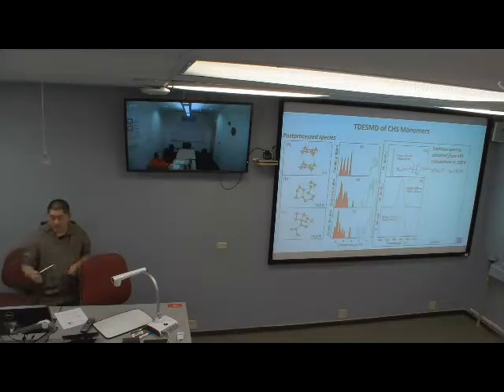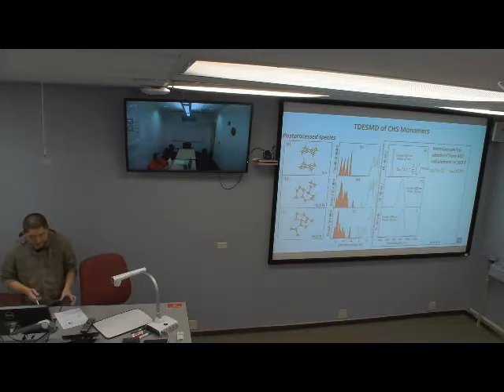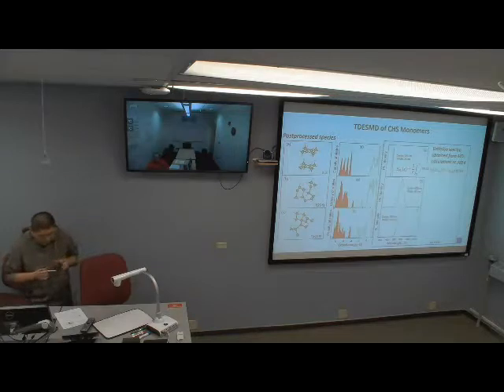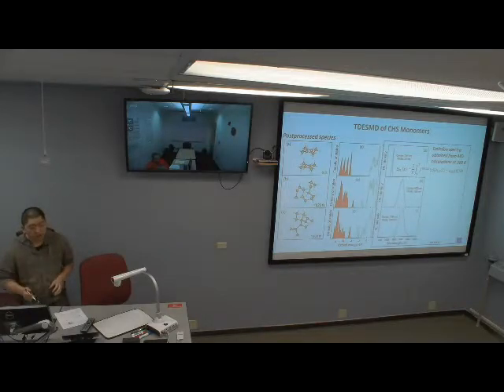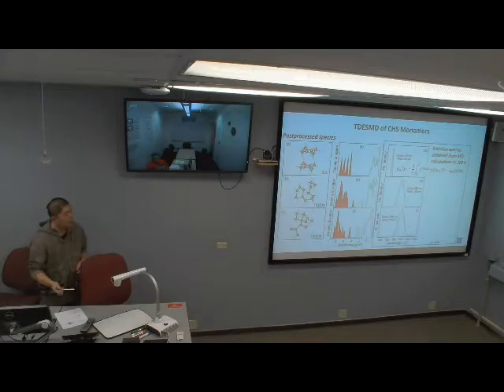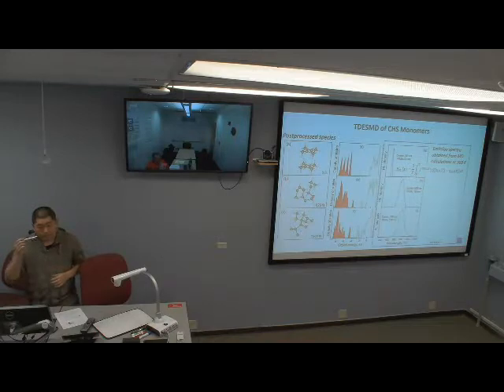So we also calculate the emission spectrum for this intermediate. What we did is we perform additional adiabatic molecular dynamics at room temperature based on the cold intermediates. And here is the equation for the emission spectrum. This equation accounts for fluctuation of orbital energies due to thermal motion of nuclei. By using this equation, we have seen there is instantaneous relaxation of any excitation to the lowest excited state. So basically we see emission is always from LUMO to HOMO. From this figure we can see a red shift and also line width broadening.